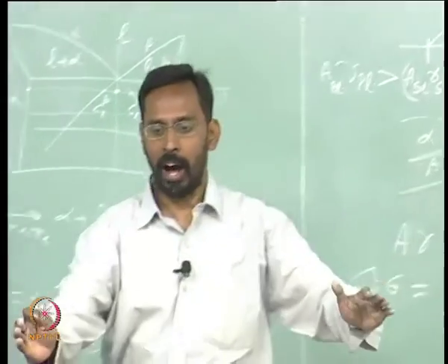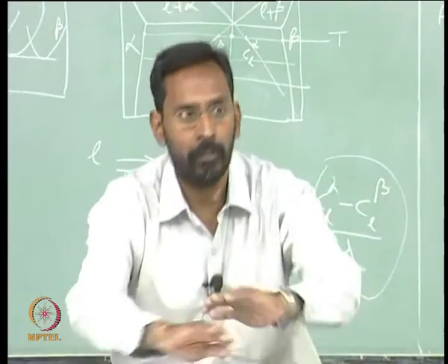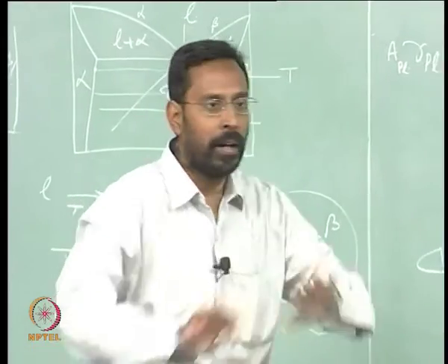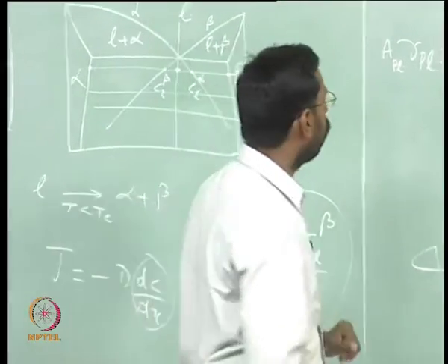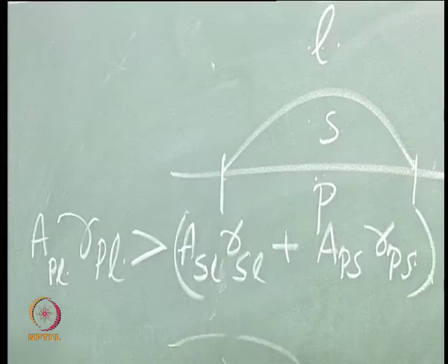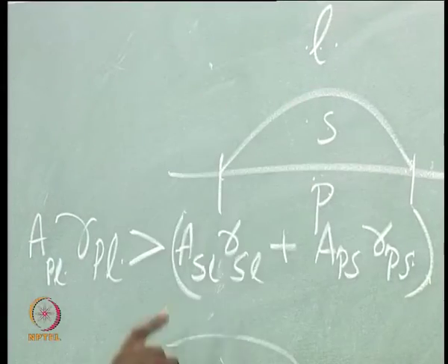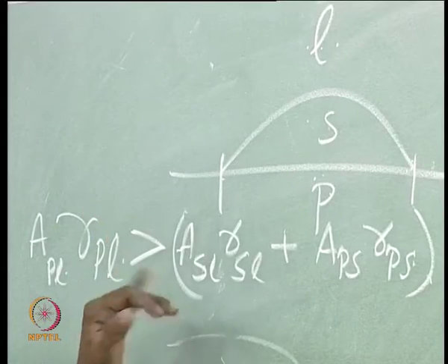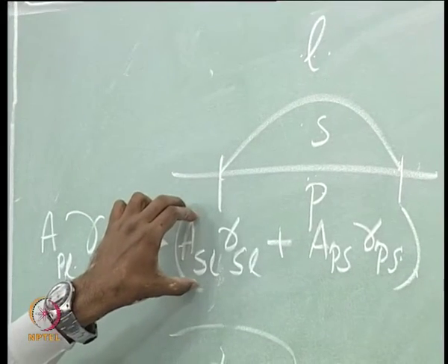This particle-solid interface is actually a circular interface, because it is a plane surface on which you have a hill forming, a bubble kind of solid, so this interface is circular, whereas the solid-liquid interface is like a spherical cap. You calculate geometrically the area of that, multiply with the gamma of that particular thing.